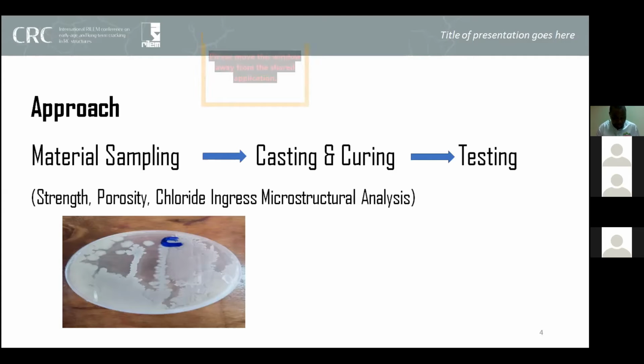In addition, microstructural changes in cracked LC3, that is limestone calcined clay cement mortars, were carried out using a scanning electron microscope before and after immersion in the bacterial solution.